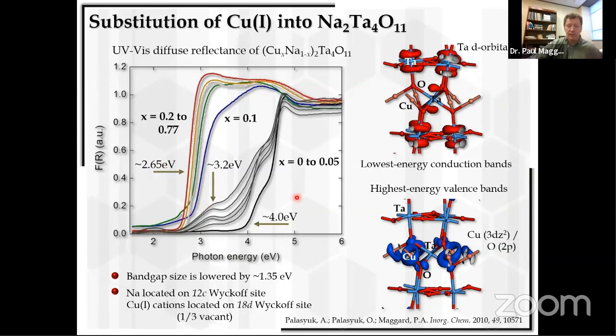And you can see in the electronic structure calculations by DFT methods that the d orbitals form the conduction band. And so you can see here are the tantalum orbitals with the electron density shown in red. And then now here are the copper orbitals with the electron density shown in blue. And these constitute the valence band, whereas these constitute the conduction band. Okay.